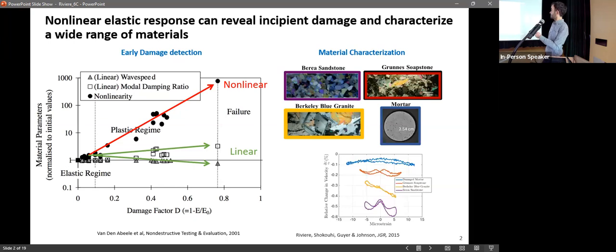We are interested in the nonlinear elastic response in general for material characterization. So there were a lot of examples given earlier today. This is just to give you an idea of what we measure in rocks. We have three rocks here and a concrete sample, a mortar sample. And those are the nonlinear elastic responses that we measure at the bottom. So you see those shapes are very different. One of the big long-term goals of our research is trying to infer, when we measure this, what does it mean about the microstructure that we're measuring? And doing nonlinear elastic measurements in rocks and granular media is great because the nonlinear elastic response is typically very large. So it's easy to measure in some ways.